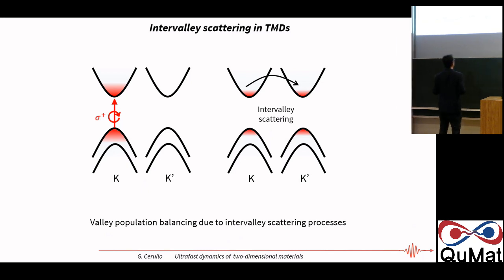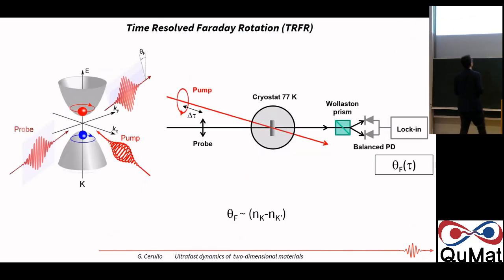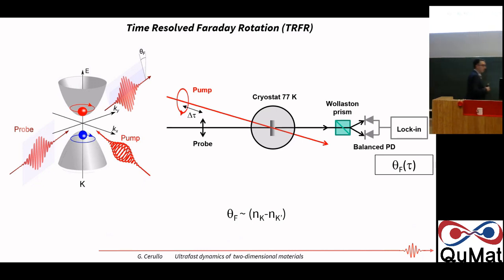So what is the technique that we use? We can use two kinds of techniques. So the first is what is called the time-resolved Faraday rotation. So the idea is that we have a pump pulse which is circularly polarized, so that creates electrons in one valley, and these electrons are also spin polarized. Now we come with a linearly polarized probe, and we measure the rotation of the polarization angle of the probe. And this rotation is proportional to the difference between the populations of spin up and spin down carriers.